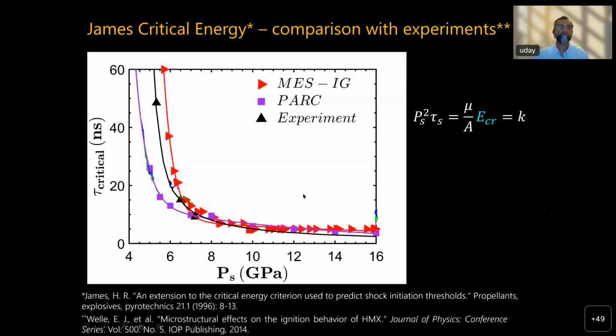And this is the envelope predicted by PARC and MES-IG. PARC is the purple one, MES-IG is the red one. So the two approaches, somewhat in the low pressure range, as you can see, there is more sensitivity and they straddle the experimental data, while in the high pressure range, they're in very good agreement with each other and also with experiment.